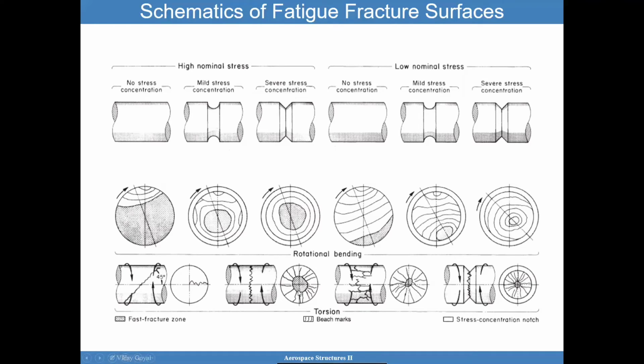When you move into a situation of a lower nominal stress, you're going to have some cracks going in this direction, but then beach marks that are emanating from, or they're just forming, and then the center here becomes the final fracture, similar to here, final fracture. And then if you have a very high stress concentration, then you're going to have the beach marks and then even a smaller area to failure. I hope this makes sense.